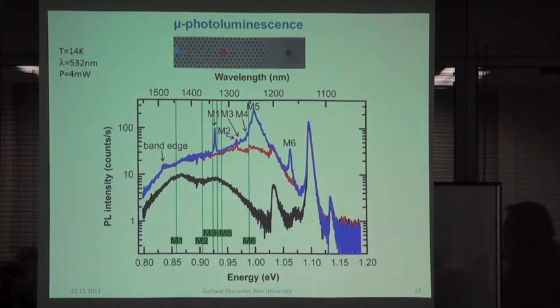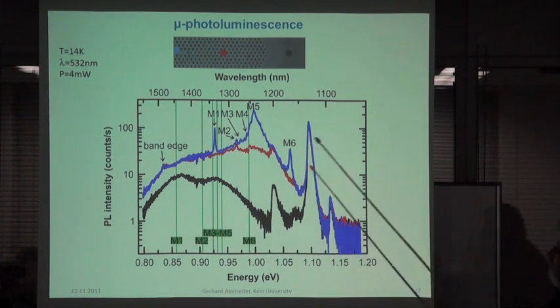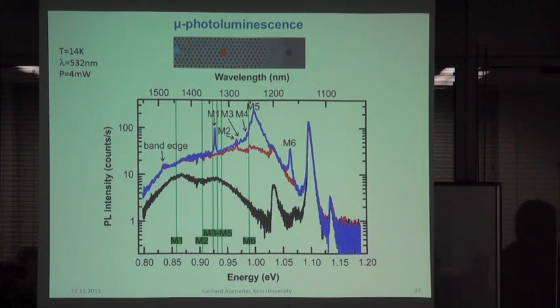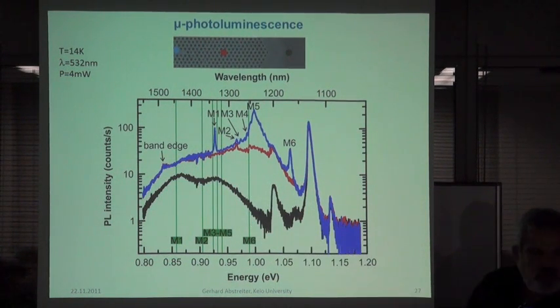Now, what do you see in the luminescence? This is a logarithmic scale of the luminescence of germanium islands. Here you see the silicon, let's say, lines. This is the TO phonon replica. This is 2 TO phonons. This is TA, which is well known in silicon luminescence. And these are the germanium islands here.